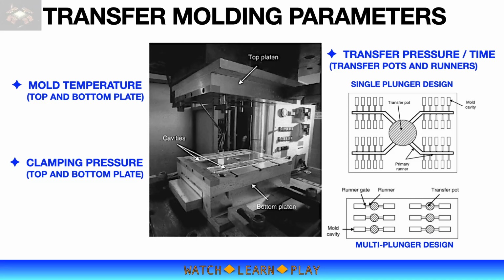For example, too high a temperature will lead to solidification of molding compound before completely filling the cavities, while low temperature will not be enough to cure the mold material. Generally, plus minus 5 degrees C tolerance is acceptable. Considering the size and number of cavities of the mold, multiple heater cartridges are installed in both the top and bottom molds to heat the cavities evenly.